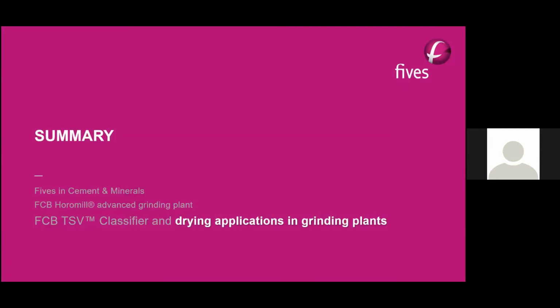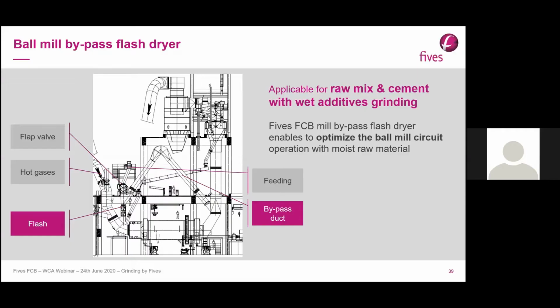So now I will continue with the drying application in grinding plants. I will present you some solutions here. The purpose of the system is to split the drying of the raw material between the mill itself and a duct called a flash dryer, which is a bypass duct outside of the mill. This system assumes that part of the material feed is fine enough to be blown up in the gas entering the flash box. This fine fraction is also most often the wettest fraction, which gives the system its relevance and efficiency.